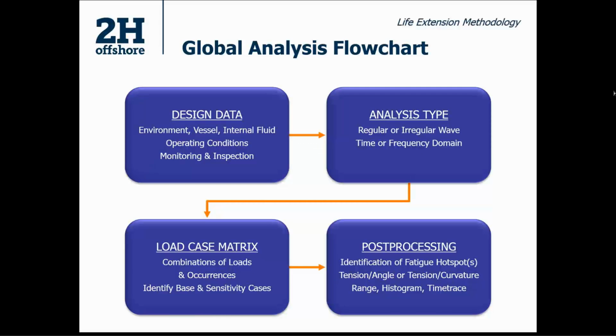And then the final step is post-processing this global model data. So this model is going to represent the system, all of the system components. So all of the risers, the ancillary devices, the floater, or whatever the riser is connected to. And what we're looking at is obviously going to be focused on fatigue. So identifying what areas the fatigue is occurring, and not just accepting the same locations that were taken at design. Things may have evolved and changed. So looking at the analysis based on the new data in order to confirm those locations, and then extract things like combinations of either tension and angle or tension and curvature as ranges, as histograms, or even as detailed as a time trace in order to go to our next step.